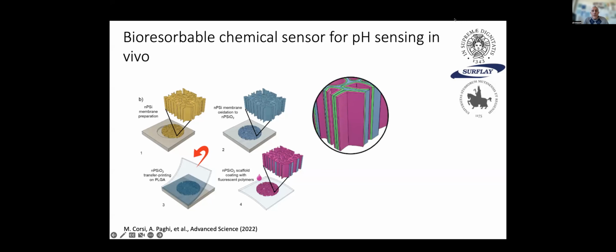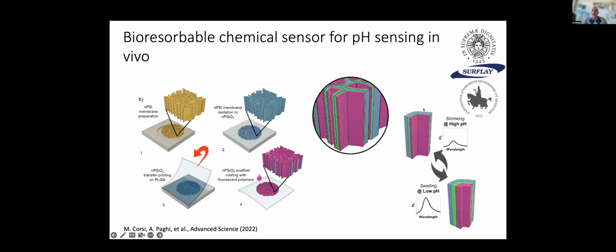But the fluorescence of the polyelectrolyte depends on how close the polyelectrolytes are to each other, because if they are very close, there is a self-quenching of the fluorophores. And if the polyelectrolyte swells, and so the distance between the fluorophores is bigger, then the self-quenching decreases. So the fluorescence intensity is modulated by the pH, because the pH changes the ionization degree of the polyelectrolyte, and in turn changes the electrostatic force that brings the polyelectrolyte together. So depending on the pH, this force increases or decreases, and the polyelectrolyte shrinks or swells accordingly.